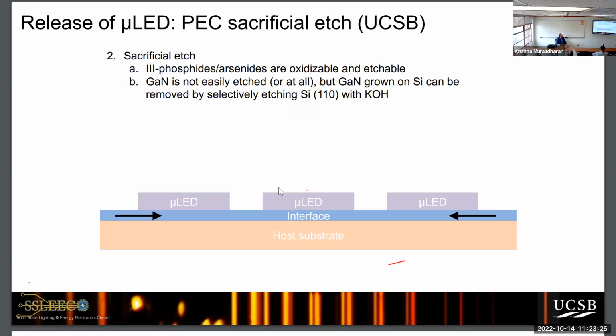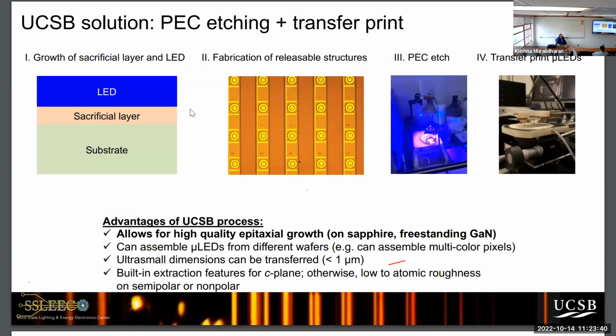One way we do a release is called a photoelectrochemical etch. We grow the LED stack and put an interface material, which can be etched off, below the micro LED, and we mount the LED to a stamp. We grow the whole structure, then fabricate rows of these LEDs on a releasable structure. A PEC etch needs blue light. Blue light generates electron hole pairs only in the sacrificial layer, and it's then etched off. And so this just shows your stamp.